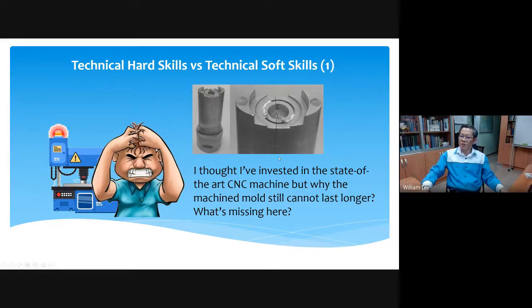So what's actually wrong with this case? From my study and investigation, it was due to improper hardening. Normally when you use tool steel as a mold, you need to harden the mold. Machining is considered a hard skill, but machining can produce only the shape, and this looks like an injection mold insert. It looks like an insert, but can it last longer? It depends on how you bring out the performance of this. It depends on the hardening. Therefore, heat treatment is also very important to know, because heat treatment will bring out the best of this material.